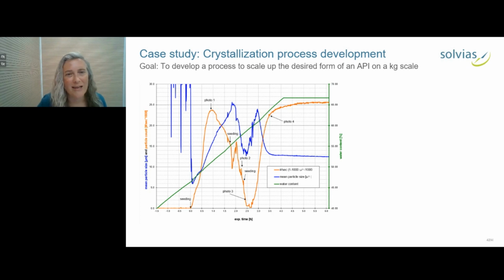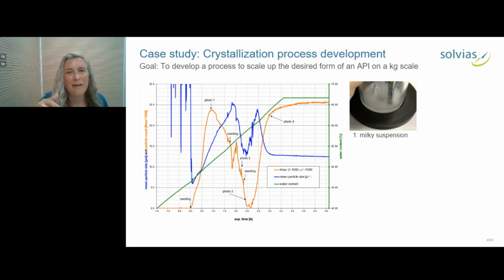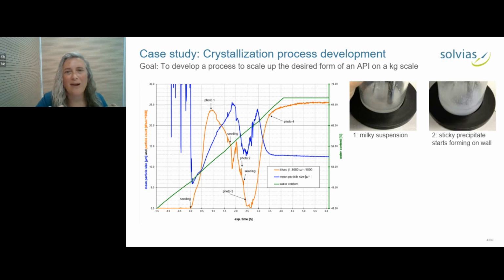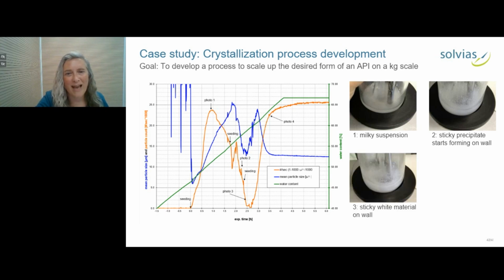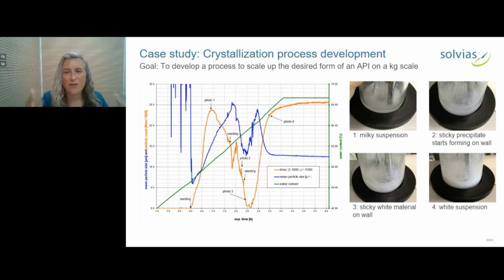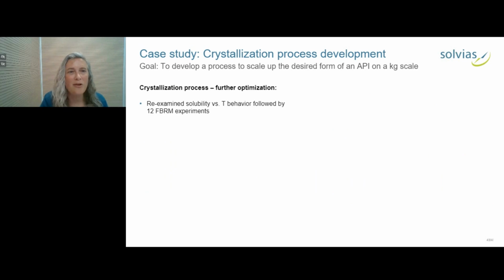The orange line is showing you the particle count. After you seed, the particle count goes up, and at the peak, you get a milky suspension. But then at some point, as you continue to add water, the particle count goes down and you start to see a gel-like, sticky precipitate forming on the walls of the reactor. This is also the case as the particle count goes very low. Then at some point with enough water, you got good behavior and had a nicely stirrable white suspension. So how do we avoid that?